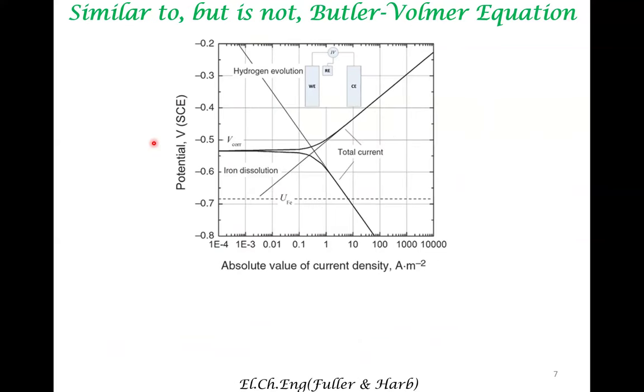Moving further, we can obtain an equation that is similar to the Butler-Volmer equation, but it is different in some manner. Okay, so remember that the Butler-Volmer equation was derived and presented for a single electrochemical reaction. It may have two components, that is the anodic component and the cathodic component of a single reaction. But here, in corrosion, we are always bothered about at least a pair of reactions, one of which is anodic and another is cathodic. So we can derive an equation that is similar to Butler-Volmer, but it is indicative of two different reactions.